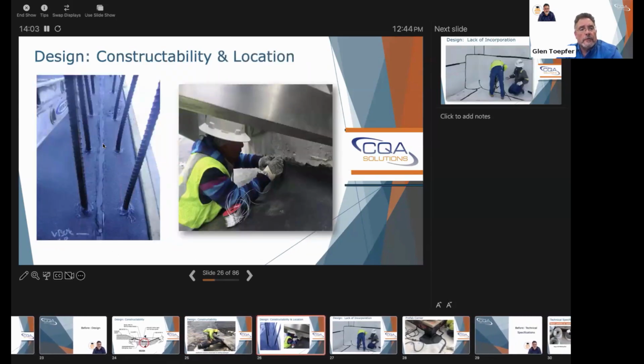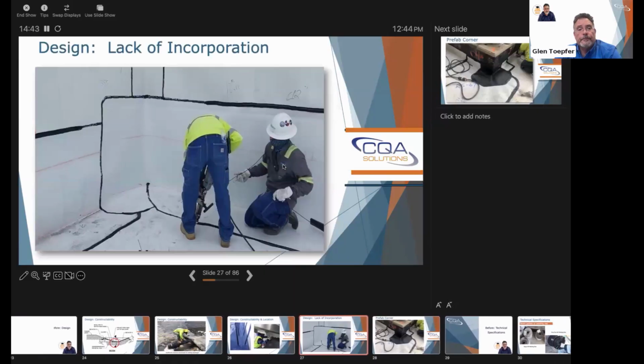Design constructability. Here's an extrusion weld that was performed between all these rebar pieces, which is hard to fit anything in to even get that done. And then they only used silicone around the penetrations to seal them. You can see in this other photo, the guy's working in a confined area. He's putting wire in for a holiday spark test, but that's a hard area to weld. How do you get uniform pressure with the extrusion gun? Those are all things that really need to be taken into account when you're thinking about any type of welding, but especially extrusion.